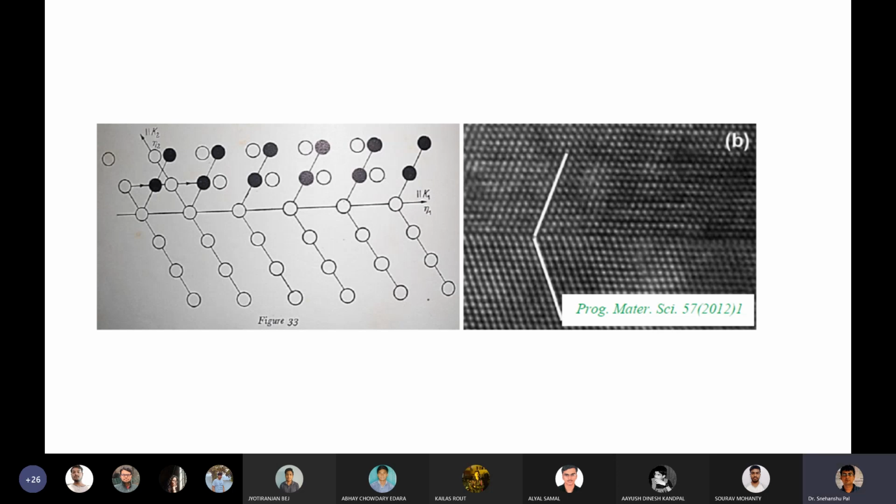So twin formation during deformation, which people call deformation twin, is very often understood to occur due to the motion of edge dislocations, which are generally partial, and those edge dislocations are of the same type. So twinning, however, requires cooperative dislocation displacement. It is very important to understand.